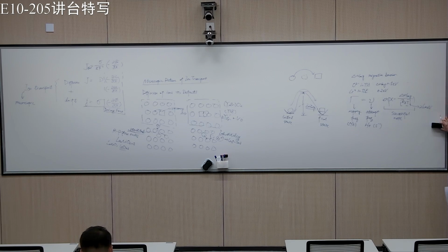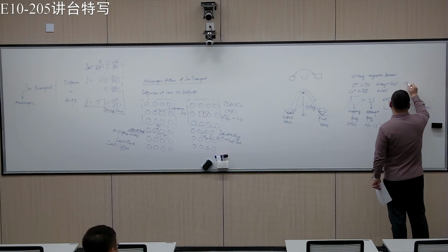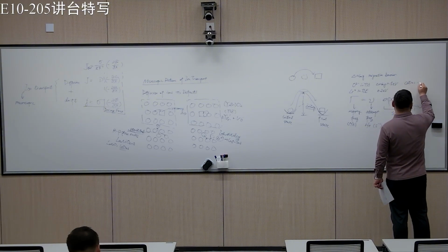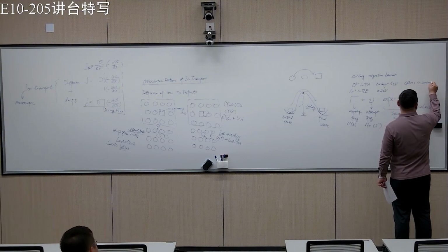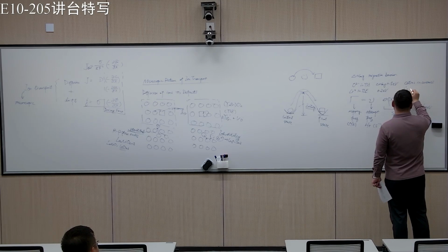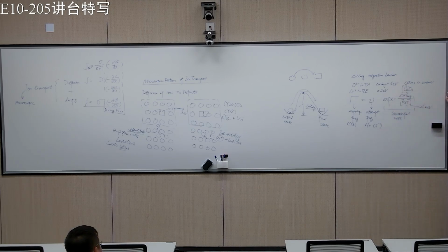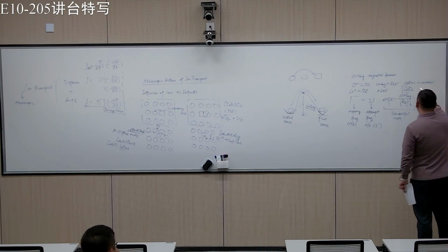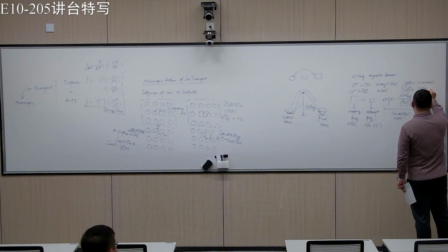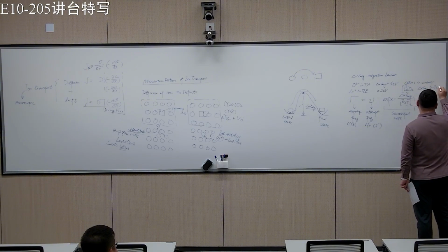Another thing is if you think of the cations in ceramics. For example, for something like ceria, if you think about cerium cations in oxide, it has a very high migration barrier. The migration barrier can be something like 6 to 8 eV.